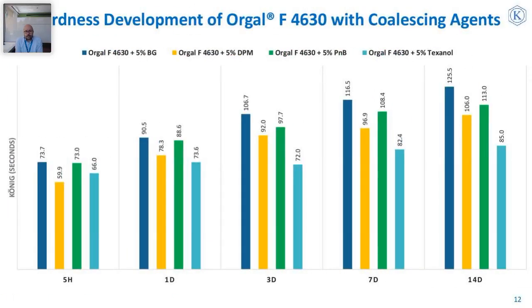Pendulum hardness values are another important property to assess early properties of acrylic emulsions, which is essential for industrial applications. Especially high early hardness values are used as an indicator for fast drying, early stackability, and early scratch resistance properties. Pendulum hardness development of our product is measured with compatible coalescing solvents after several drying periods. As indicated in the dark blue and green bars, butyl glycol and PnB give the highest early hardness development values after 5 hours of drying, and this similar trend continues up to 14 days.